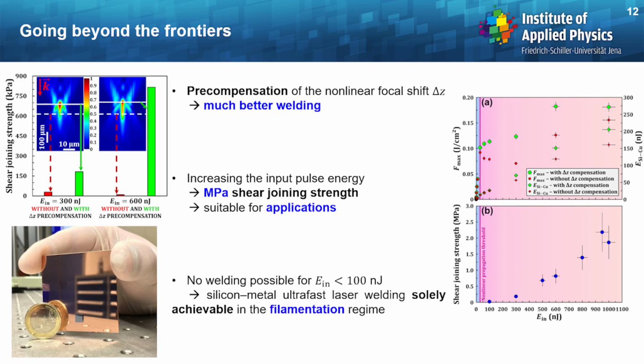Interestingly, here you can see that no welding is possible for input pulse energies below 100 nanojoules, which simply means that silicon to metal ultrafast laser welding is solely achievable in the filamentation regime. And this completely justifies our approach to characterize the nonlinear propagation.